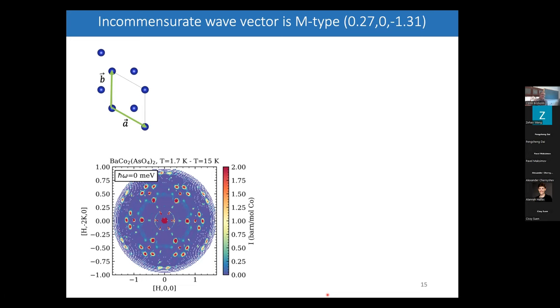Sure, but the symmetry can just tell you how many domains you can have. The intensity variation is the most interesting one, but maybe something suppresses one of the variations, not having to do with the domain population. You could have that kind of impression, but that's not the case because we have, for example, this peak is weak, but this peak is strong, but they belong to the same domain. Okay, I got it, not the domain population. This looks like an equal occupation of the three different types of domains that we could have.